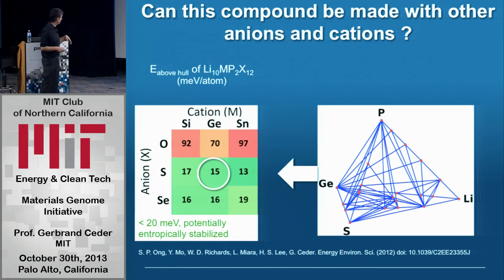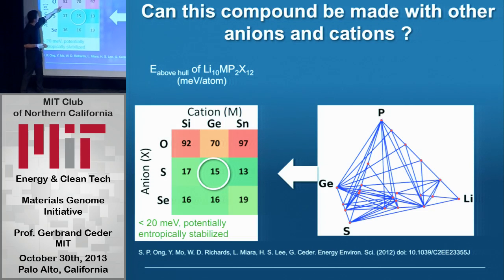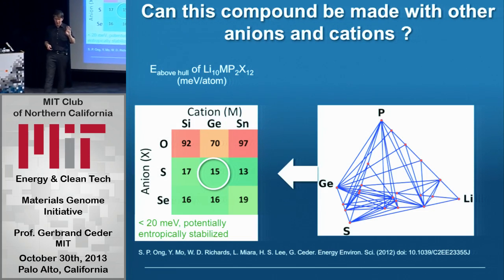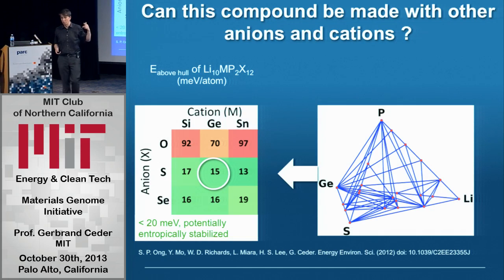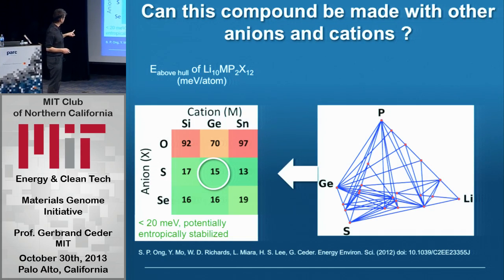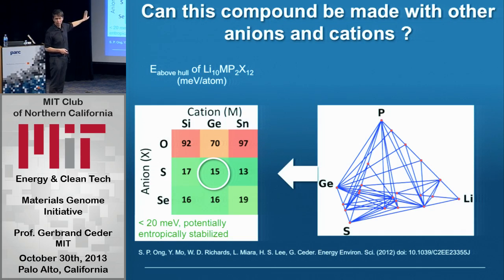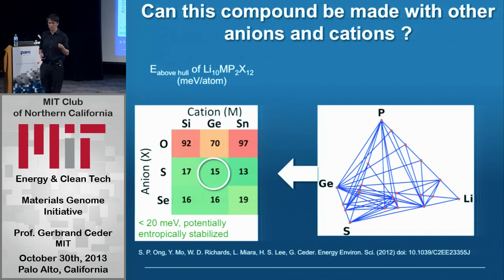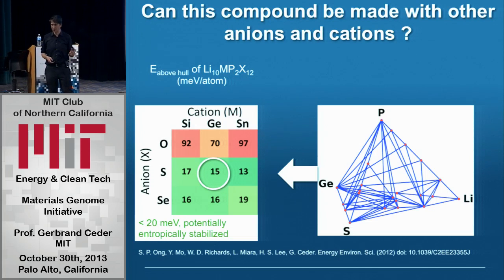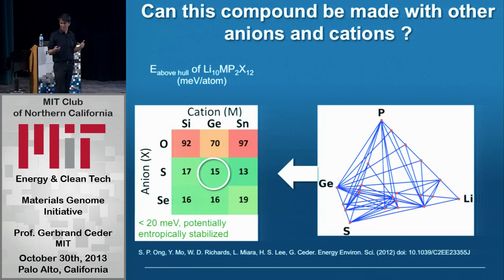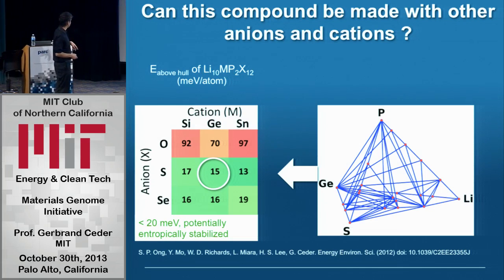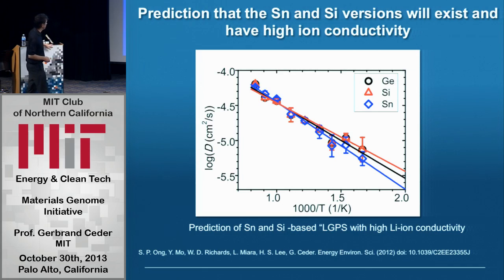Usually, we can keep the material stable. And what you see is that if you keep the sulfide and you replace germanium by silicon or tin, you have about the same number. And that's good news. That means that if you can make the germanium version, which we know you can, you can probably make the other ones. But the bad news is, if I replace the anion by oxygen, that number goes way up. And we predicted that it would not be possible to make the oxides. And that's bad news. Okay, so the glass is half full, right? So we predicted that the silicon and the tin version would be good. They have great conductivity, just as good as LGPS. So we put that out a year after the initial material came out.